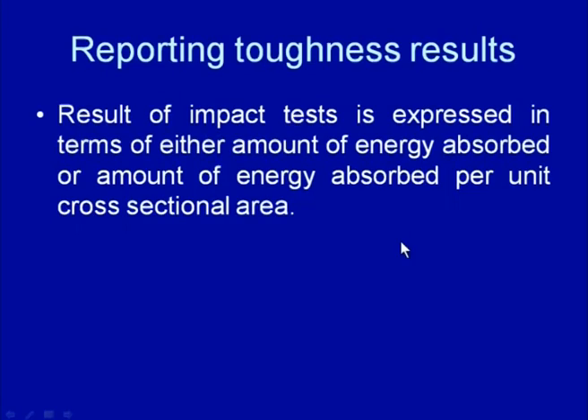So, if the material requires very little energy for fracture to take place, that will indicate lower toughness of the material and poor ability of the material to withstand impact load conditions. Once the impact test, this toughness test, is completed, the results are reported in terms of the amount of energy absorbed by the specimen in this process, or the amount of energy absorbed per unit cross-sectional area is also reported.